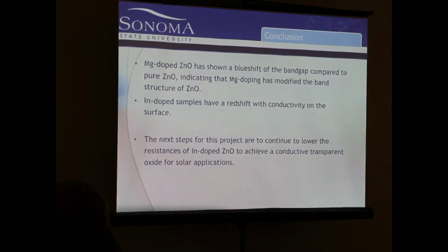And so really the conclusion of the project is that magnesium doped zinc oxide has shown to really blue shift, so widen the band gap compared to just zinc oxide, as well as indicating that magnesium doping has really modified the structure of zinc oxide, which is something that we got to see. As well as the indium doped samples had a red shift, so we got to get some conductivity on the surface, which was one of the main goals.